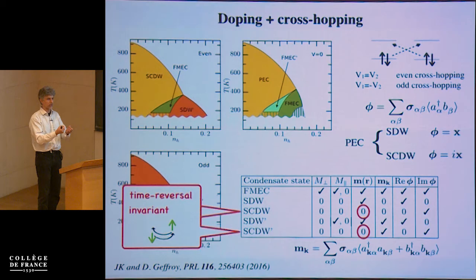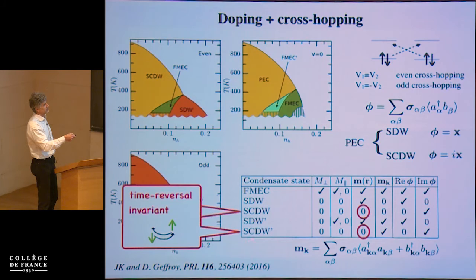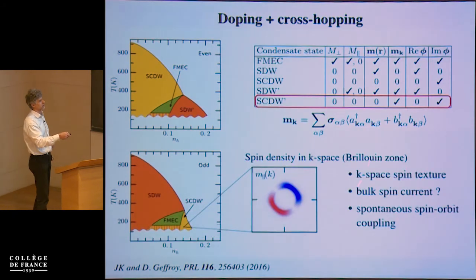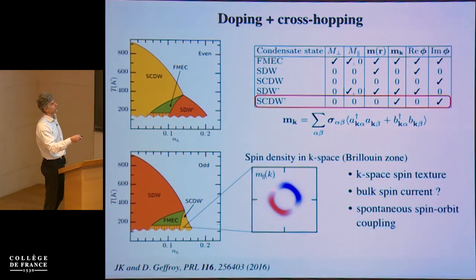They flow on the same atom between orbital A and orbital B, while in this SCDW phase, we actually get a spin polarization that we can see in the K-space, and this is the actual calculation of this quantity.